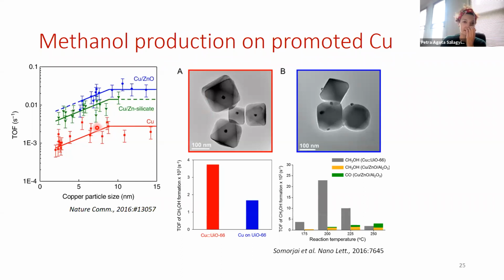And also because it's a site-selective reaction, there is a minimum of 8 nanometer particle size at which optimum activity is observed. Now, 5 years ago, Somorjai's group looked into some quite interesting work. They used the UiO-66 framework, with terephthalic acid, and they used 18 nanometer copper particles in 2 different ways. On the one hand, they built core-shell systems, so they built the MOF around the copper particle. In the other case, they decorated the MOF particle surface with the copper nanoparticles.